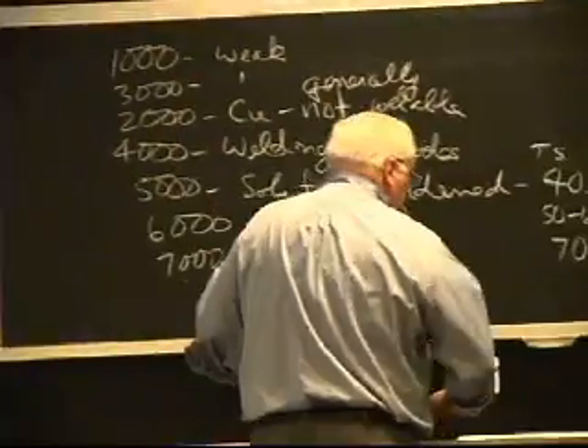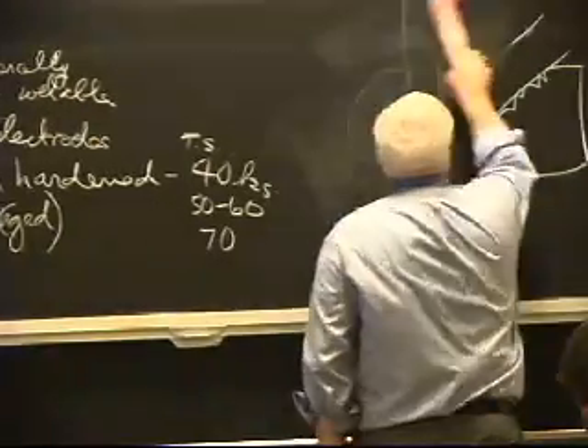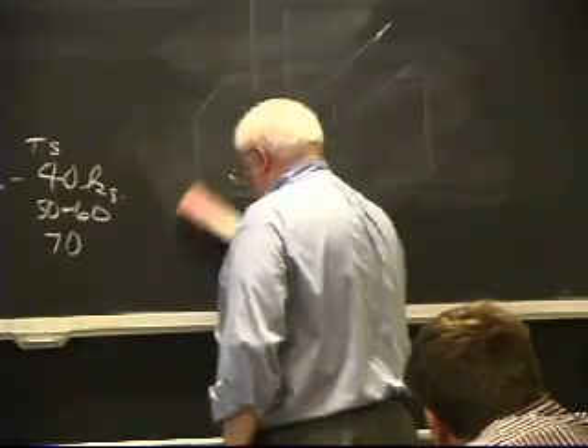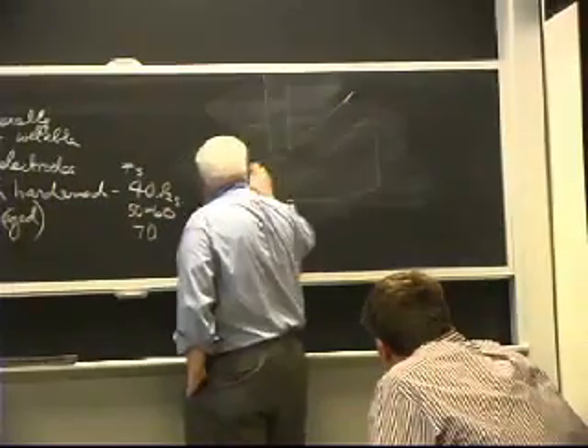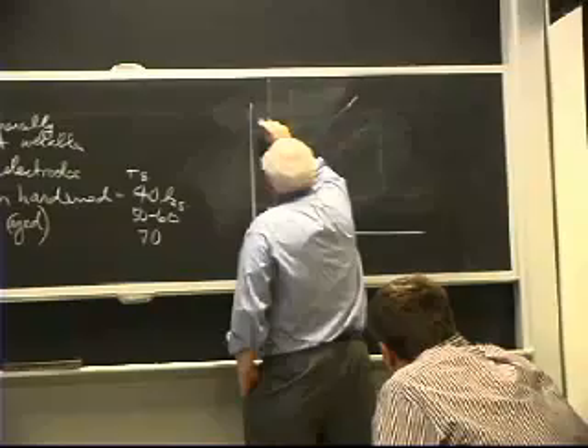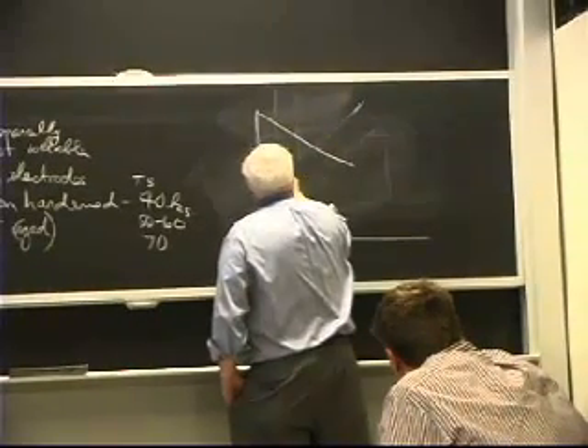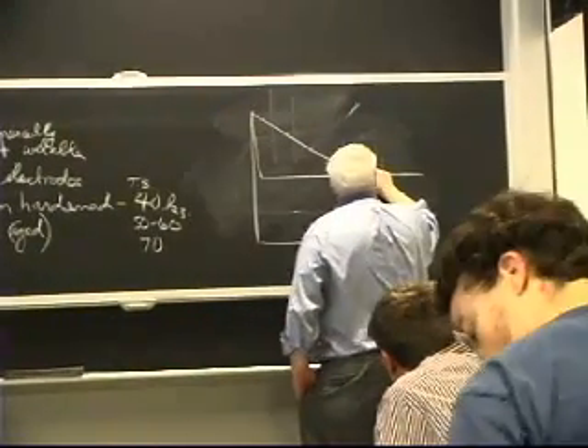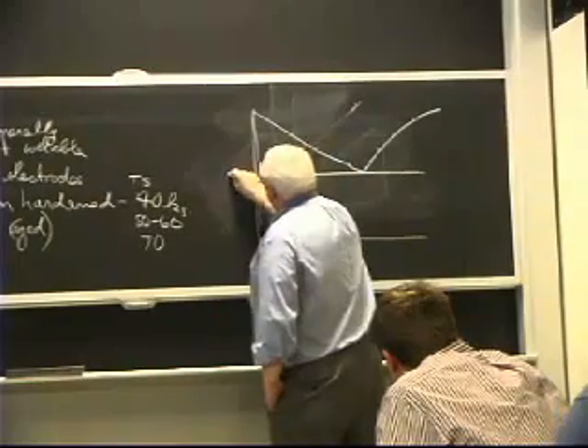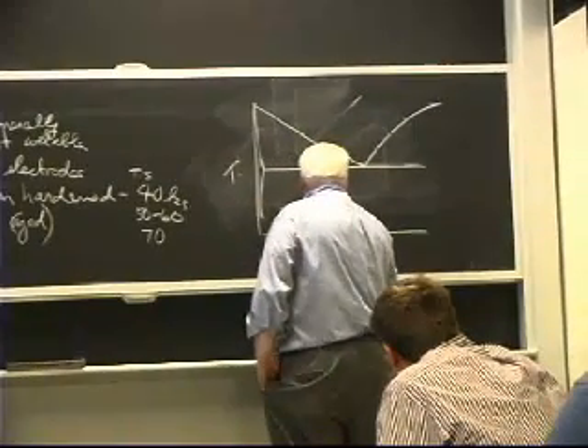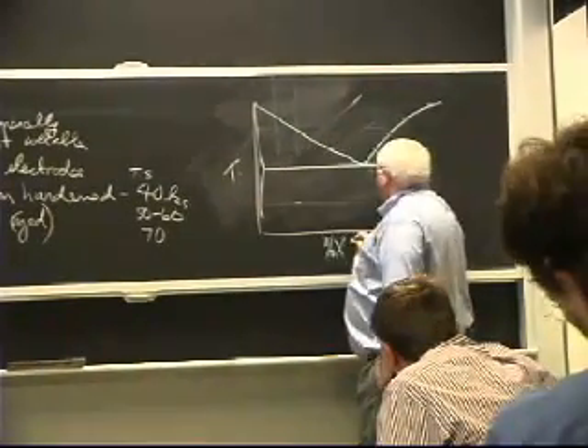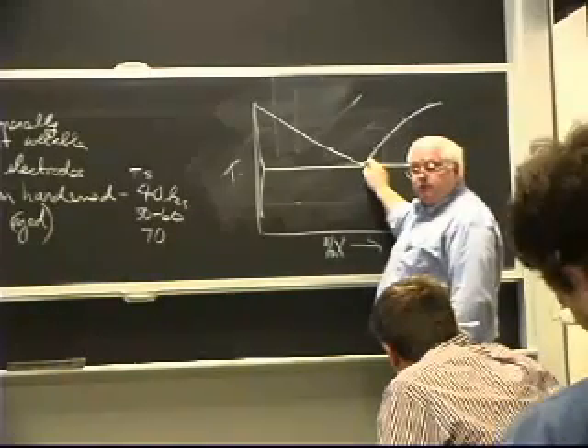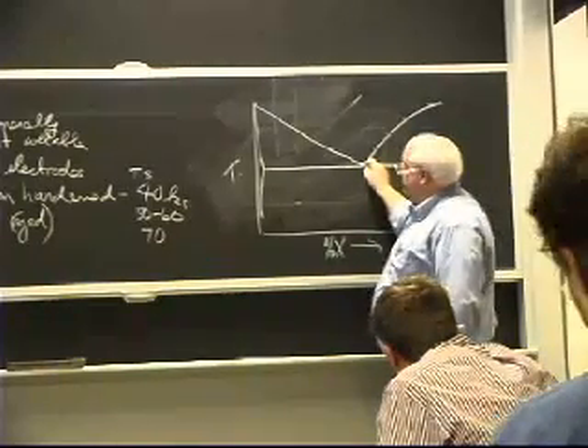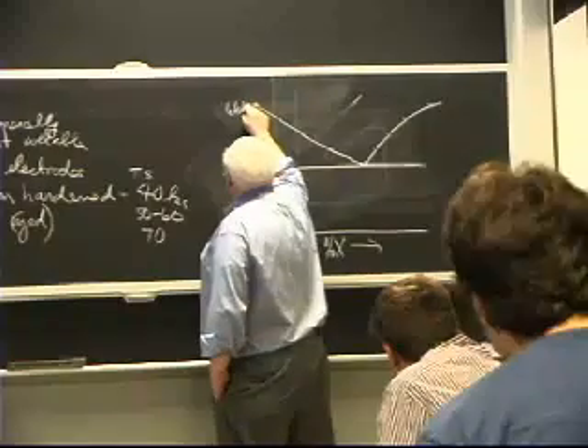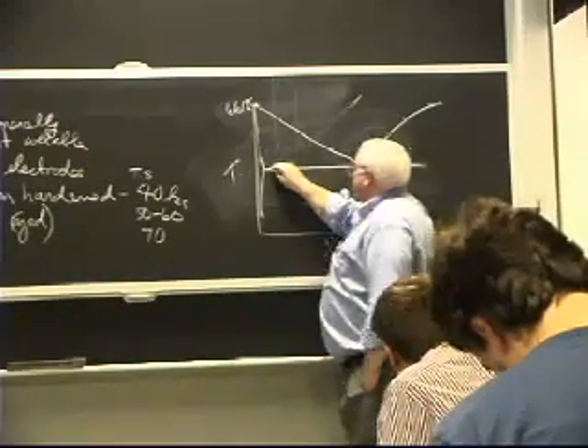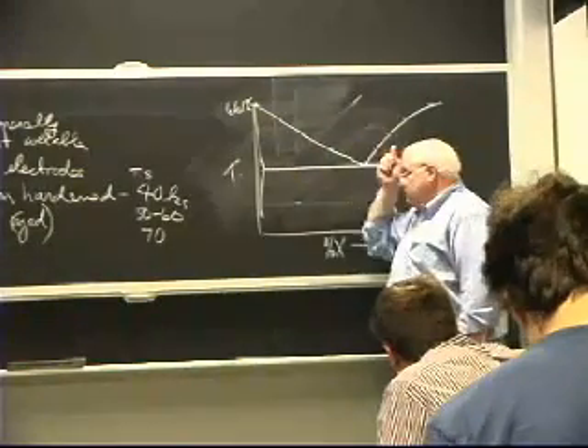Now all of that can be understood fairly simply by looking at the phase diagram for aluminum. It doesn't really matter whether you're looking at aluminum silicon, aluminum copper, aluminum magnesium. This is temperature, this is percent X in the alloy. They form eutectics with all these other things. So this is 661, that's the melting point of aluminum in degrees centigrade. This is going to be down around 520 or something like that.